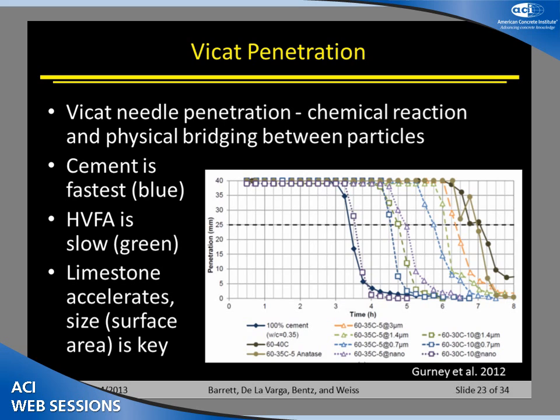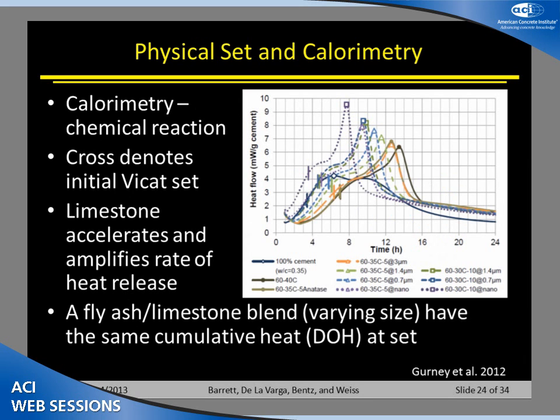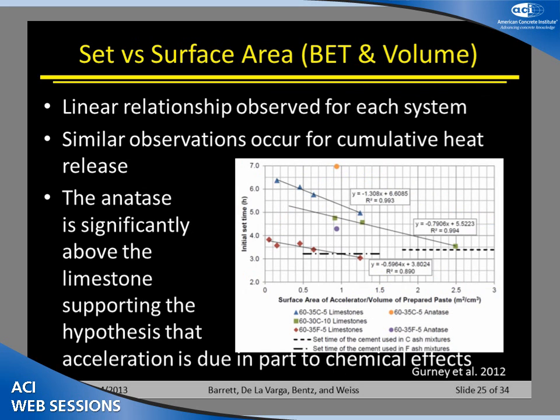What I want to point out is that this is the conventional or baseline system shown here in this dark blue line, 100% cement. If we just start to add fly ash to the system, here we look at our 60% cement, 40% ash system, we would be way over here. So we go from about a 3.5 hour set time to about a 7 hour set time. If we start adding limestone into that system, this moves back over to this position. If we take some of this data and plot it a little bit differently, we can see similar trends with calorimetry. But if we plot this differently, based on the surface area of the limestone being added, based on its size, we can actually control when that set time would be.